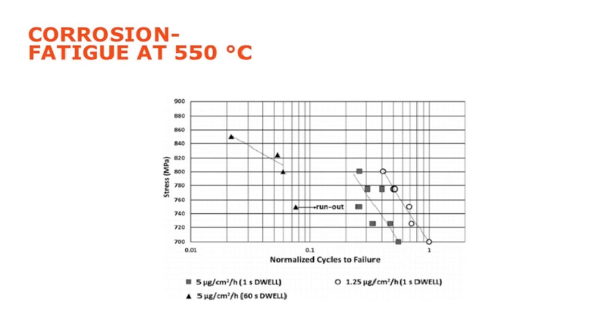If we compare the two 5 microgram results to start with, one is a 1 second dwell, so this is a trapezoidal test, where we're ramping up the stress and holding it. That dwell time represents holding the stress at a maximum value, and then we're ramping it back down. So we've got a 1 second dwell and a 60 second dwell. The 60 second dwell test, the triangle, has a lot more corrosion occurring per cycle than the 1 second dwell. So we can see more corrosion in that case, worse fatigue life.